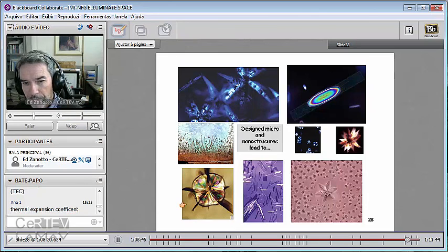If you look here in this particular microstructure, there's a glass phase, one single crystal, and cracks being nucleated. Another problem related to glass ceramic processing is that the thermal and elastic properties of most crystals are different from the thermal and elastic properties of the residual glass phase. If they are above a certain critical limit, and people have published on this, you can calculate the level of residual stresses, and they can lead to spontaneous cracking, which is no good in most cases. But this can be calculated and measured.